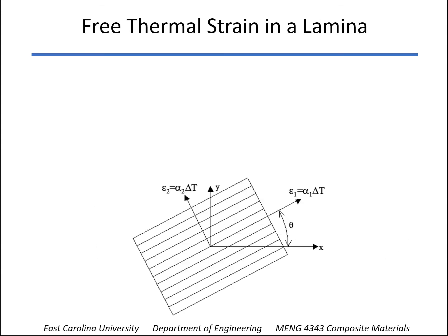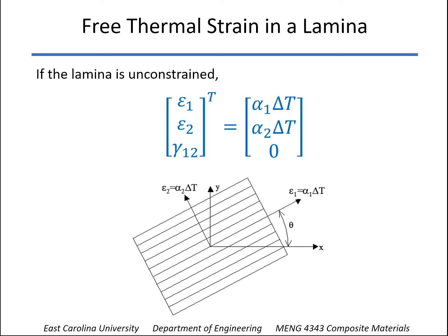So let's talk about free thermal strain for just a moment. Here's a composite layer, just an arbitrary orientation for now. If we don't have any constraint on the laminate, just like with an isotropic material, if we take an aluminum bar and heat it up and we don't constrain it at all, we're not putting any stress on it, but it will grow in all directions. Now in this case, certainly with a fiber reinforced layer, the thermal coefficients in the fiber direction and transverse to the fiber are going to be different.